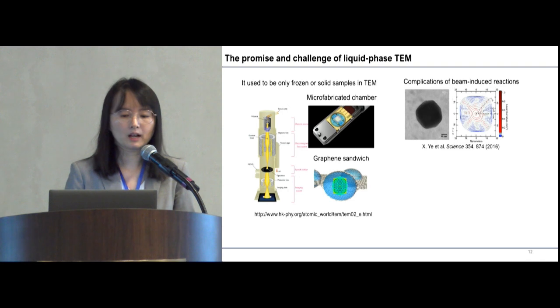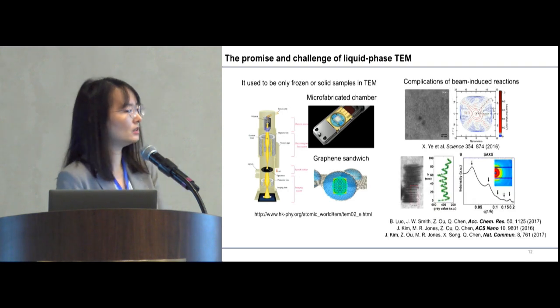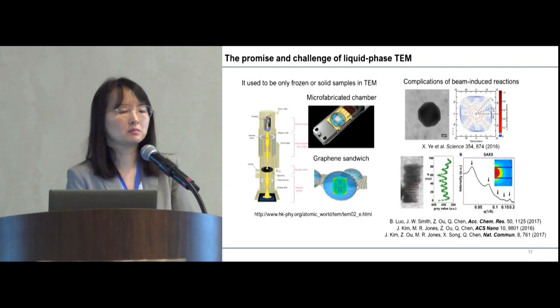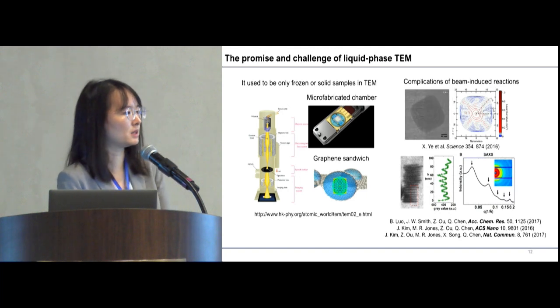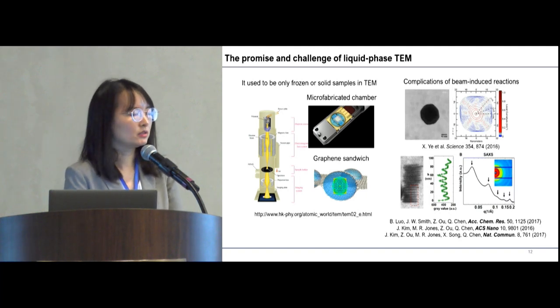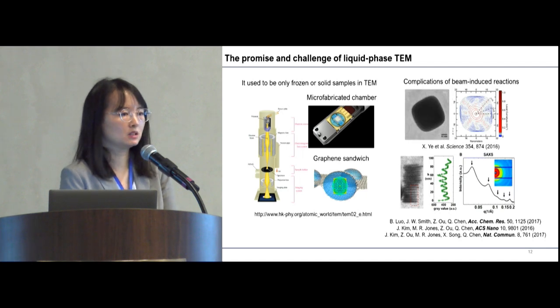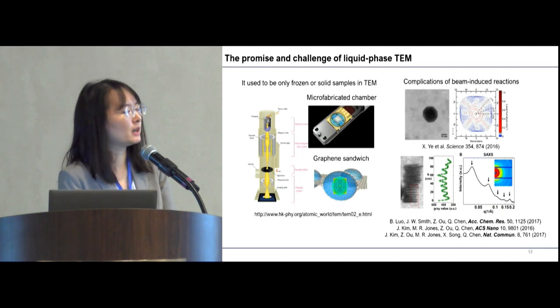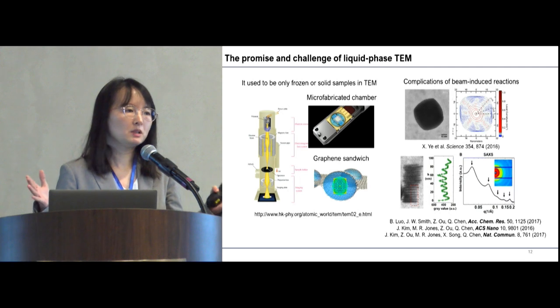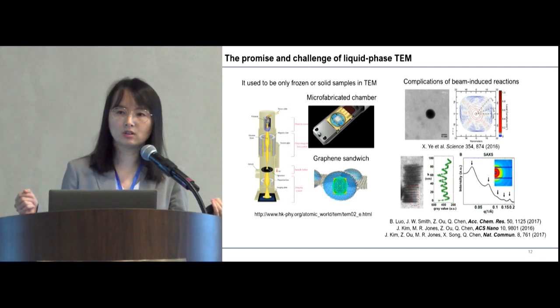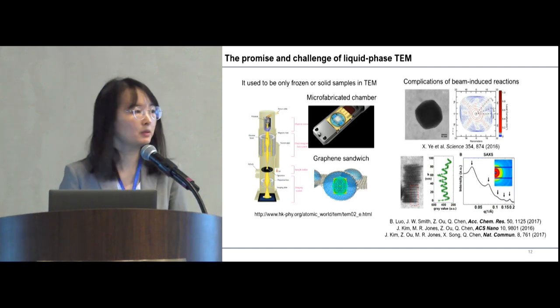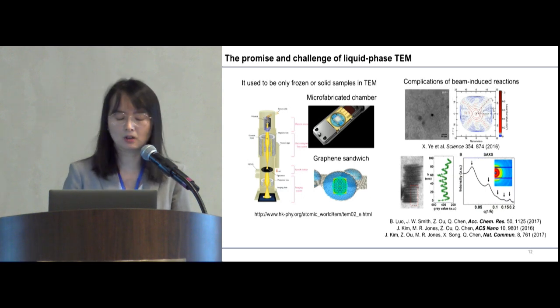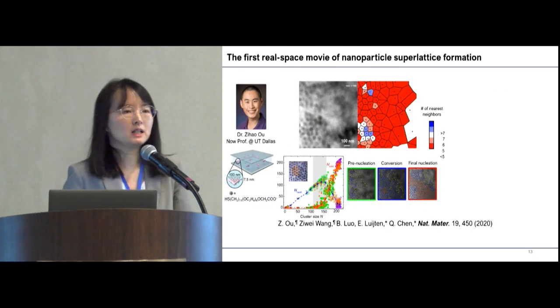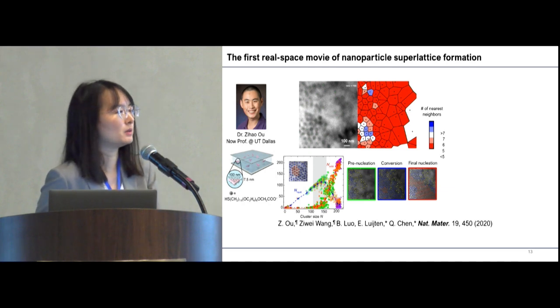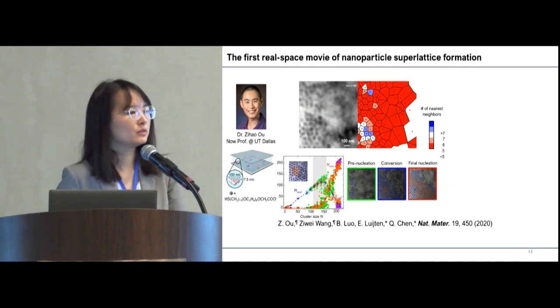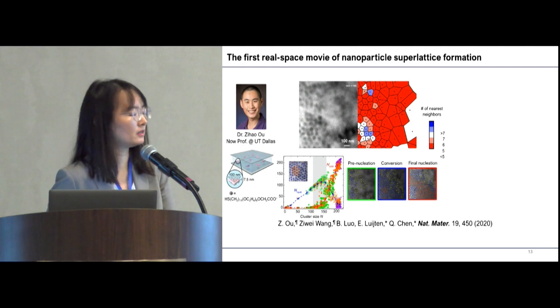So that's why when I started my career 9 years ago, the first few papers coming out of my group were essentially control experiments funded by my NSF Career Award by the Solid State and Materials Chemistry program, where we were able to identify an imaging dose condition within which we do not need to worry about nanoparticle reactions induced by the electron beam. So with that being established, in 2020, we published our first paper on liquid phase TEM imaging of nanoparticle self-assembly.